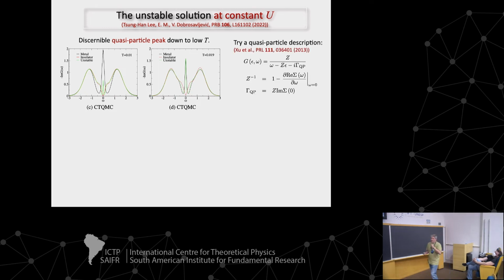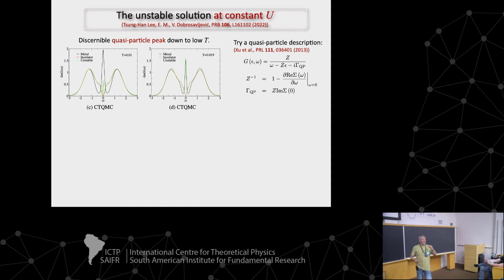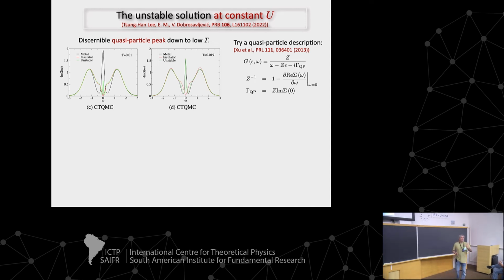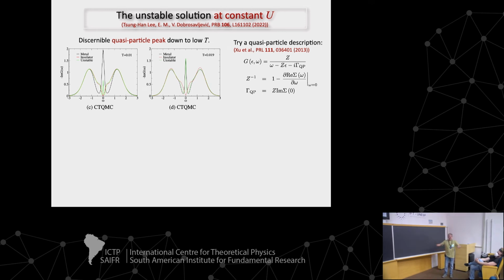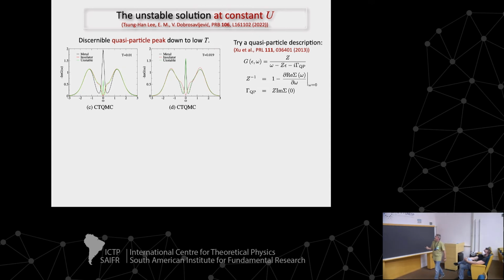So what we did was the following. If this is a peak, let's try to describe this as you would a normal Fermi liquid quasi-particle. A quasi-particle in a Fermi liquid has a Green's function that has this behavior. This Z is the so-called quasi-particle residue. There is an imaginary part that gives you the scattering time or scattering rate that you can calculate. All these things can be calculated from the self-energy that you got from the solution. So this is basically a Fermi liquid parametrization of the Green's function.